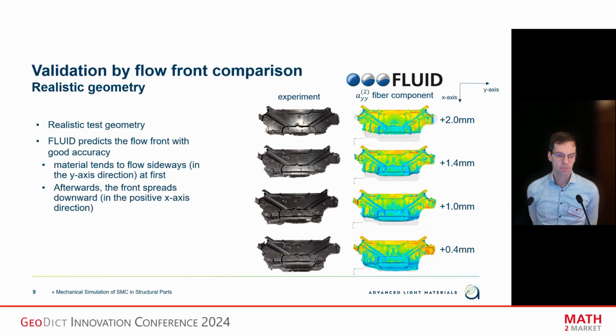And finally, we did a validation for a realistic geometry, where we had a filling study performed by partners and compared it to the flow front obtained with the simulation. And actually, we saw that we could predict the flow front with good accuracy, as you see here on the pictures.